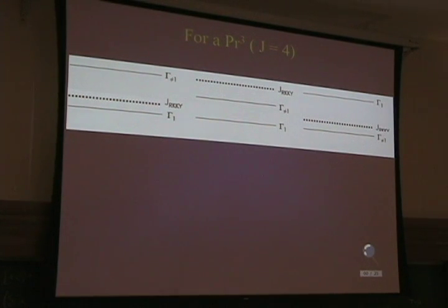I mean, for other rare earths, for the non-Kramers ones, that's very easy to see, right? Let's take praseodymium. You can have an RKKY interaction in a praseodymium system of, I don't know, 10 Kelvin, 20 Kelvin, right? But if you lower the temperature and you have a singlet ground state which has no spin, the system will not order, right? There's no spin there. But if the RKKY interaction is high enough that you actually are seeing a crystal field state that has a spin, the system may order.